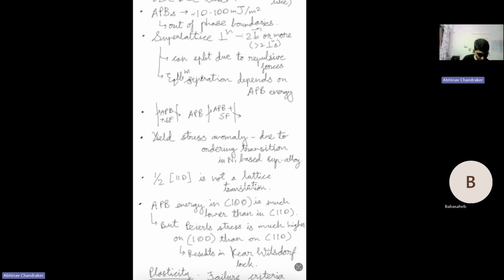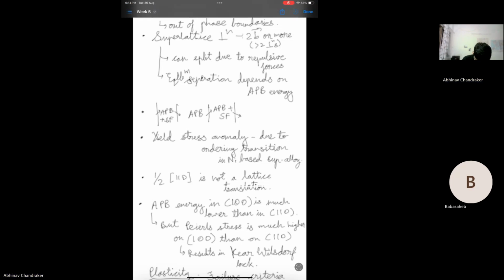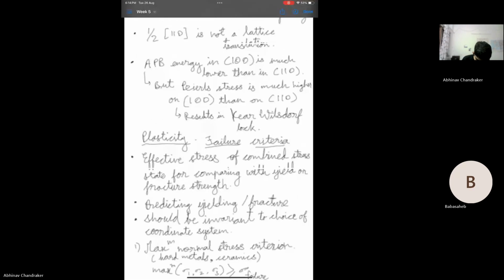So what will happen is that here, let me show in these notes, you will have a stacking fault getting created because the dislocation has split into partials, and between the two partials we have the stacking fault, as we saw is the case in FCC material. This is for L12, and in between the two dislocations which split into partials, there will be an APB forming. So it's this region. The equilibrium separation will depend on the stacking fault energies and the APB energy, but we'll have this kind of situation.